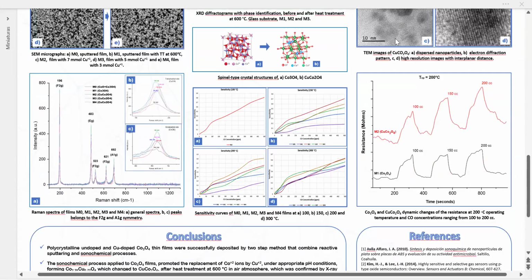Raman spectroscopy was also used to study the vibrational modes and structural changes. All samples show 5 prominent peaks with different symmetries, as can be appreciated in the spectra. The peak located at 196 wave numbers is owed to the representative tetrahedral sites with copper ions, and the peaks at 692 wave numbers belong to the representative octahedral sites with cobalt ions. No additional peaks were observed, indicating purity of the copper cobaltite spinel.